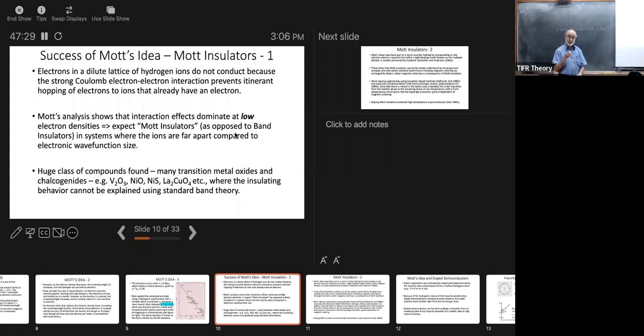But then you ask yourself the question, what about 2 electrons on a hydrogen atom? The second electron, it turns out, is very weakly bound. It's bound by 1/20th of a Rydberg. It's barely bound. So clearly, there's a large electron-electron repulsion taking place. Roughly 1 Rydberg of repulsion, so that the second electron is barely bound. Or 95% of the Rydberg is the so-called U for hydrogen atoms.